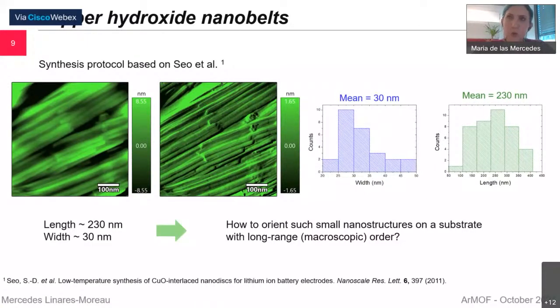I mean, we always synthesize the MOFs, at least the first layer, from the ceramic to MOF conversion from copper hydroxide. You can create these MOFs and synthesize them solvothermally using other salts. So I wouldn't know. From this mechanism of conversion, I wouldn't know how to compare it.